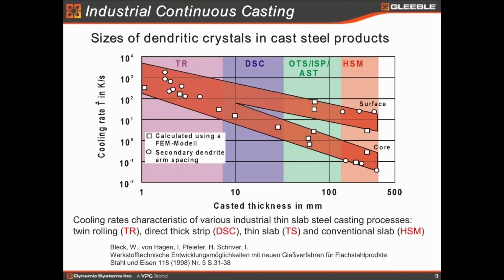And this figure shows the dendrite size, crystal size, at different thicknesses of the slab, from like 500 millimeters thick down to 1 millimeter or 1.5 millimeters. You can see that when the thickness becomes bigger, the secondary dendrite arm spacing becomes bigger too. And vice versa, when the thickness is 1 millimeter or a little more, then the structure is very fine. And for thin strip casting, the cooling rate you will see in the real production flow could be up to 1,000 degrees C per second. That is very important to simulate in the Gleeble. And with the Gleeble, we can quench as high as even 10,000 degrees C per second. So the Gleeble again gives us a lot of capability to study all the casting and direct rolling processes.